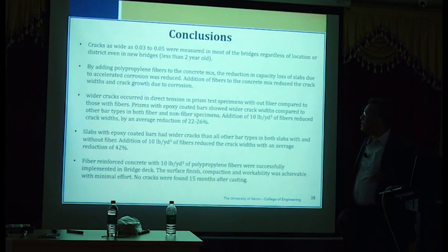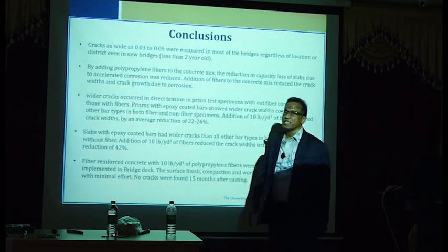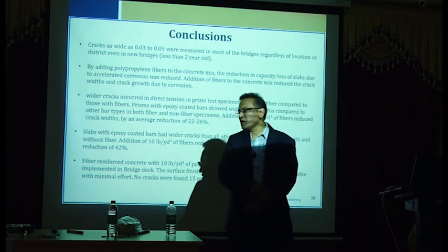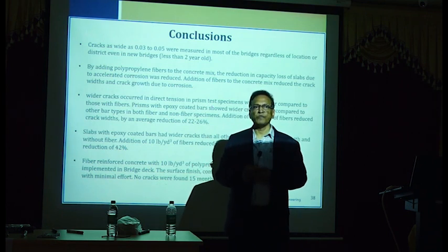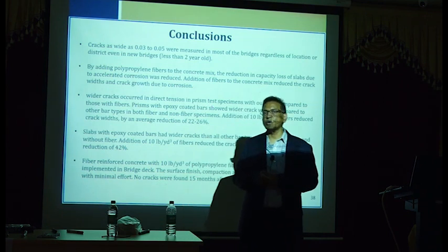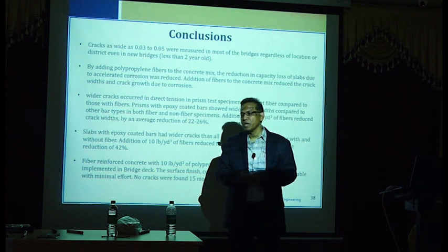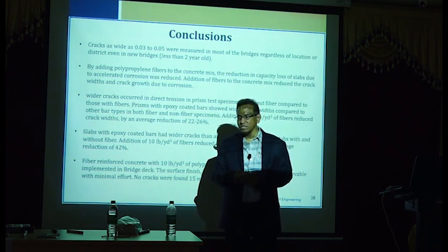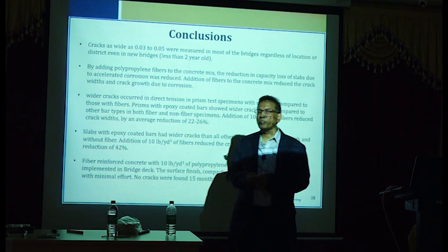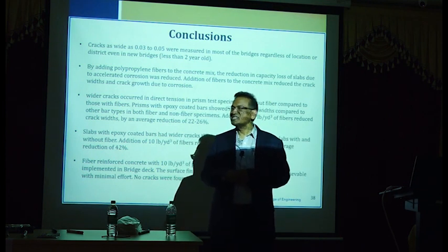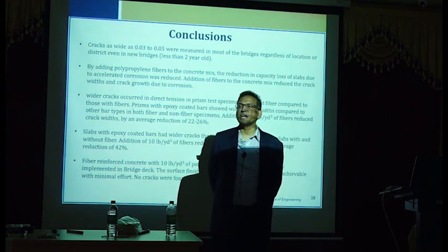And then we looked at this. I think I'm missing one or two slides. But anyway, the gist is, in summary, we found that fibers have really helped in controlling crack widths. So the ACI 222 limit of 0.007 inch is not achievable with the current specifications.